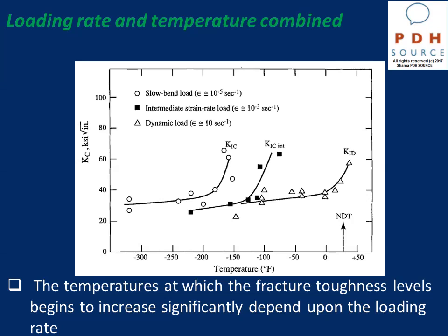So basically, this temperature for static is around minus 190. For intermediate loading rate, it's around minus 125 Fahrenheit. For dynamic, it's around 25, which is very, very significant.